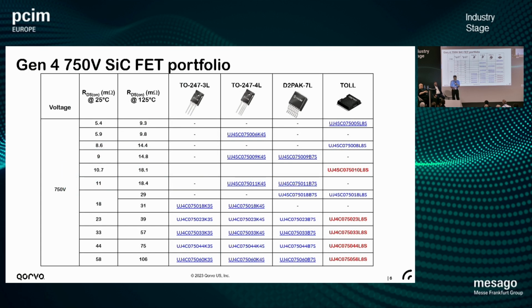And so that's what our portfolio looks like now. You'll notice that this portfolio is largely focused on relatively low RDS on devices. There's not a lot of high RDS on devices. So we tend to focus on where this cascode arrangement and the JFETs will make a difference. So there's a lot of low RDS on examples in there. And you can see that TO leadless portfolio has a couple of parts in blue, which are released, and a couple of parts in red, which are coming soon. And then there's a D-square pack 7-lead portfolio of 750 volt devices, essentially the same RDS-ons, starting from 9 milliohm going to 60.